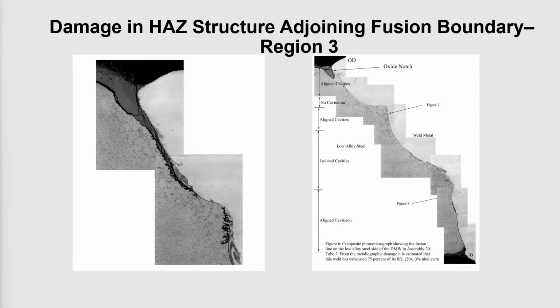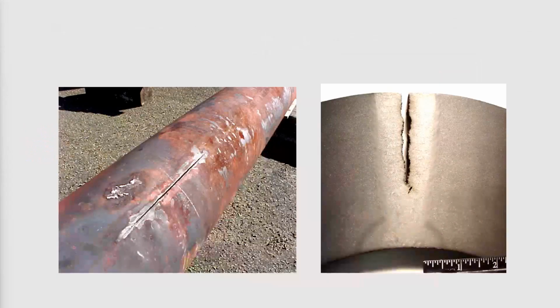And then there's the classic example of the damage in the heat affected zone immediately adjacent to the fusion boundary in the dissimilar metal welds. Excuse me, the old dissimilar metal welds that used to be made with austenitic stainless steel filler metal. In those cases, the damage was preferential in the heat affected zone due to decarburization that occurred and due to the mismatch in the coefficient of thermal expansion. I'll show you examples of damage in this stack bead configuration running across the artificial, continuous heat affected zone created in the weld deposit itself.